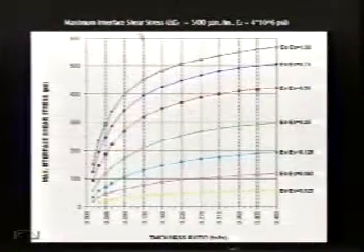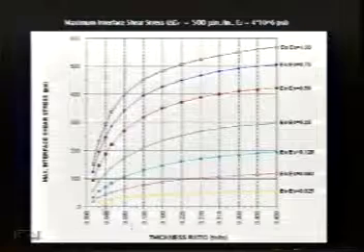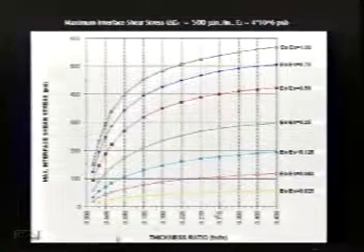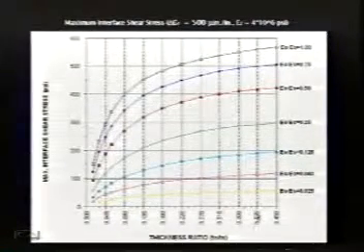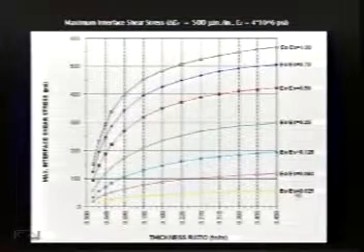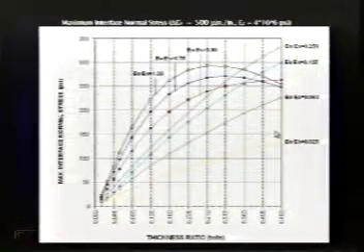This happens to be the one for normal stress. This is the one for interface shear stress. Again, you can see that in this case, as the thickness of the overlay increases, the stresses go up. This shows an increase for the modulus of elasticity.